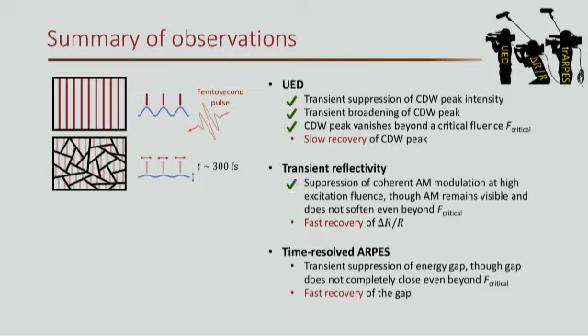On the other hand, the suppression of the coherent amplitude mode can be explained by the fact that in these small puddles of charge density wave, there's a loss of long-range coherence. That's why you do not detect the coherent oscillation in the delta R over R signals. I'll come to the fact that the amplitude mode doesn't soften and remains later. It also explains the transient suppression of the gap, where there's still a suppression of the amplitude of the order parameter, which is essentially being probed by the gap size in ARPES.